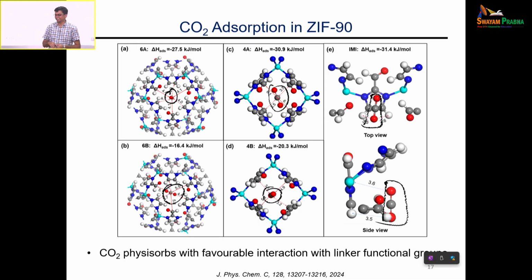Physisorption? This is physisorption, okay. If you look at it very carefully, the first and the second images, let me just delete the markings. I am not sure if you are all able to see the distances. They are all of the order of 4 angstrom plus. At a molecular scale, that is pretty large, okay. It may not be very obvious, but the linear shape is almost held as well. We can do analysis and show it is not changing so much. All of this is physisorption, okay.